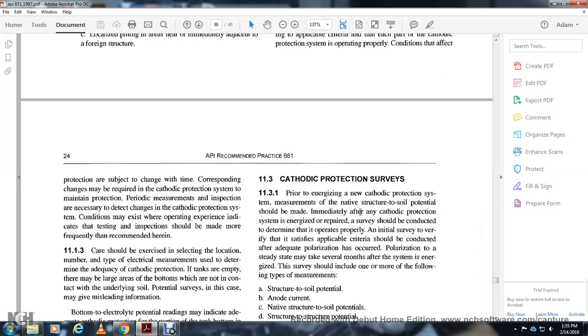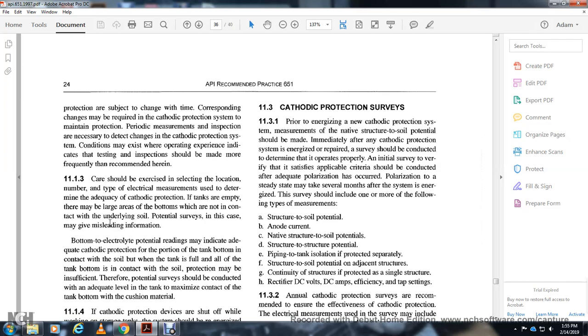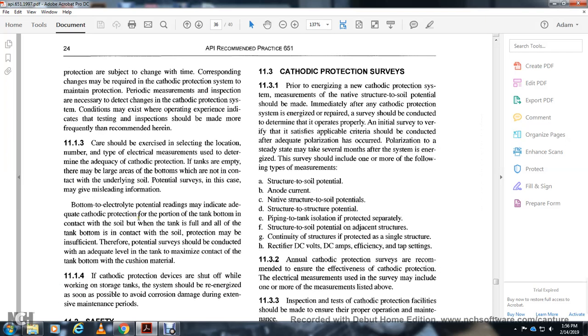Periodic measurement and inspection are necessary to detect changes in the cathodic protection system. Testing and inspection should be made more frequently than recommended herein if other experience indicates it. Care should be taken in the location, number, and type of electrical measurements used to determine the adequacy of cathodic protection within the tank. In an empty tank with a large bottom area in contact with the underlying soil, a potential survey may give misleading information.